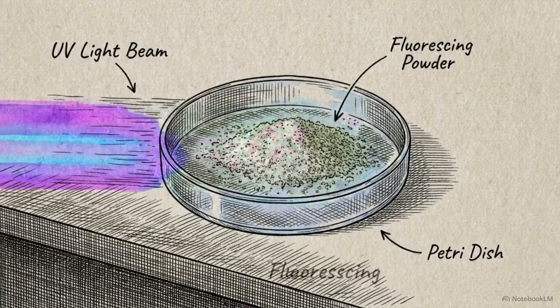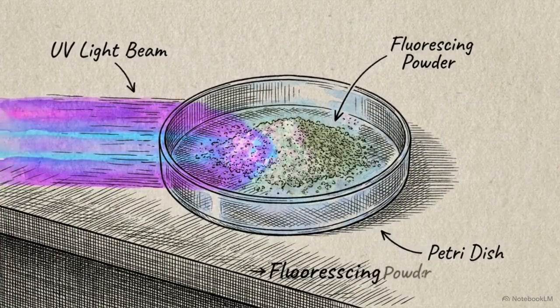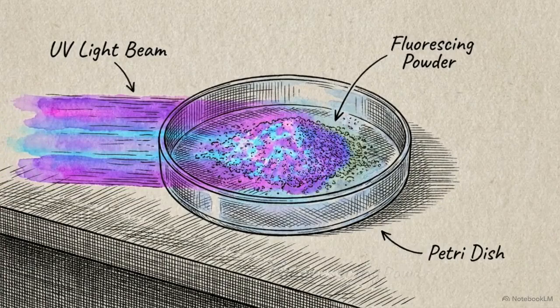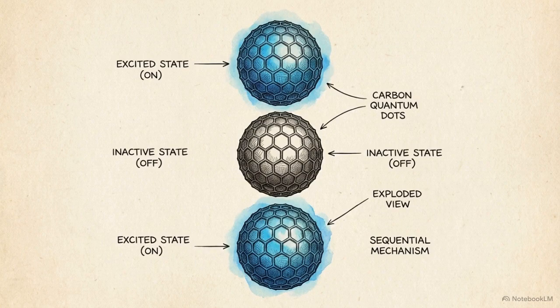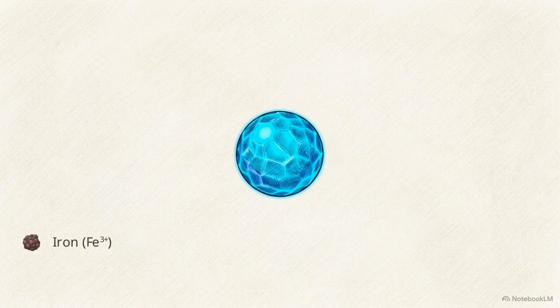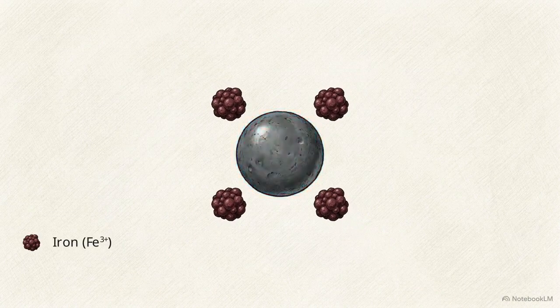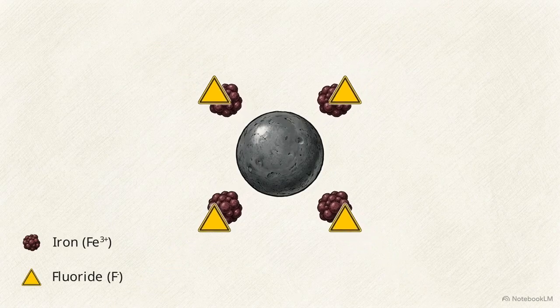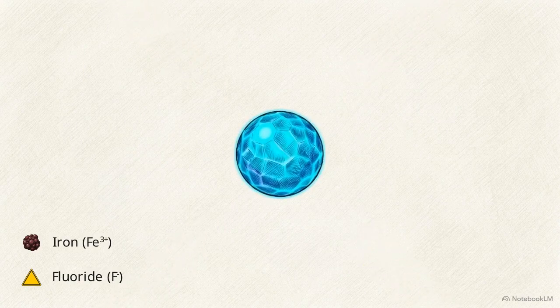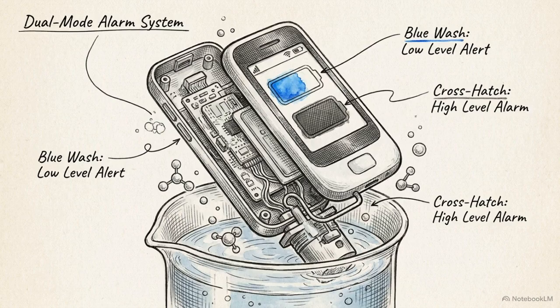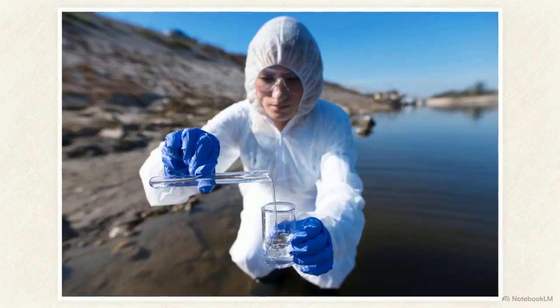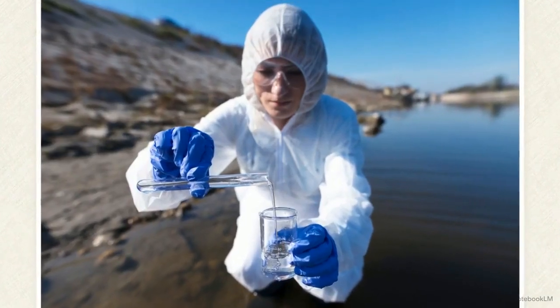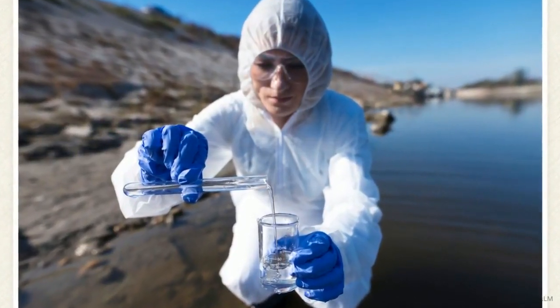These newly formed dots have a distinct baseline capability. When exposed to UV light, they fluoresce with a brilliant, intense glow. This creates a unique on-off-on mechanism. If iron is present in a water sample, it binds directly to the dot, instantly turning the light off. But if fluoride is introduced, it aggressively reacts with the iron, stripping it away and immediately restoring the light. This microscopic chemical reaction translates into a highly sensitive, dual-mode alarm system. We can use the exact same batch of dots to test water supplies for two entirely different, invisible pollutants.